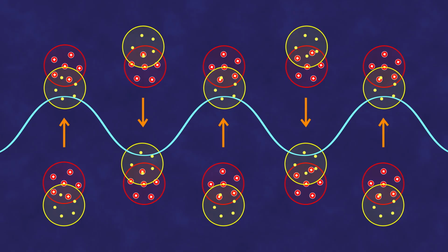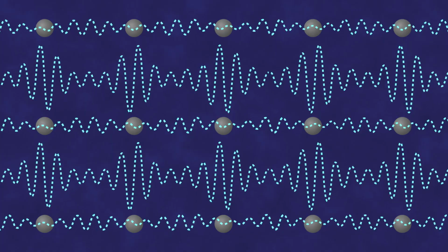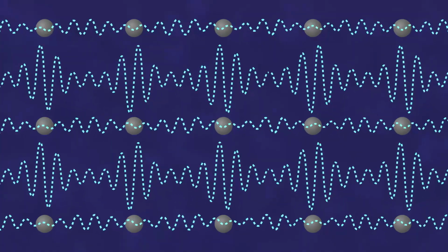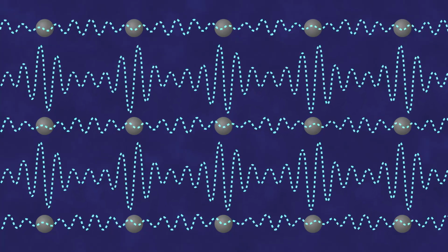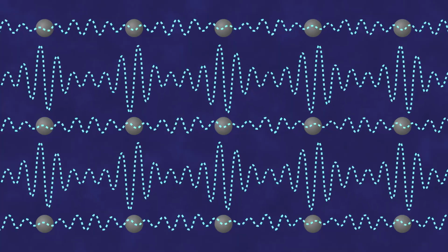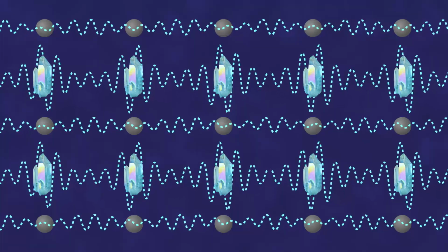As a result, the field is greatly weakened near the nanoparticles themselves, but becomes strongly enhanced in the gaps between them by tens or even hundreds of times. These are the so-called hot spots, and if we place upconverting nanoparticles in these hot spots, the efficiency of upconversion increases accordingly, by hundreds or even tens of thousands of times.